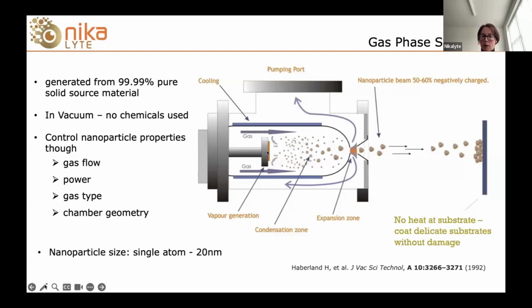So let me explain a little bit about how it works, and then I can talk a bit about the features and the controls. The technique is based on a process called magnetron sputtering. In this image here, this is the magnetron head. We have a target of solid source material, usually a metal or a metal alloy. And we apply a voltage to that target and then put some gas in front of that target. In this case, it's argon gas. And that argon gas is ionized, and those ions basically hit the target and knock off atoms of the material. So you can see these little atoms here floating around inside the chamber.